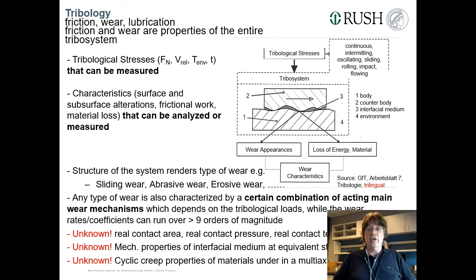What can be analyzed afterwards are the wear appearances or phenomena, so how your surface looks like. We can measure the loss of frictional work or frictional energy, and we can certainly measure some loss of material, so the wear loss. While there is no direct relation between the two, this is what we call the wear characteristics. But when we analyze, for instance, the structure of the system, which is macro scale, you can do this with a bare eye, this gives you just a name for the problem. So we call this type of wear sliding wear, abrasive wear, erosive wear, you name it. You might know all these terms, but it does not give you anything else. So you do not know what is really going on at the surface and maybe even below the surface.